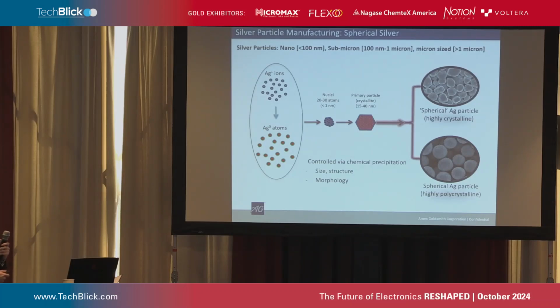Overview of silver particle manufacturing. Like I said before, we make our silver nitrate. So we go from our silver ions via a chemical precipitation process to silver metal. In this case, there's an initial nucleation step where 20 to 30 atoms of less than a nanometer coalesce, and then they are either slowly grown to form these primary particles or crystallites that range between 15 to 40 nanometers.